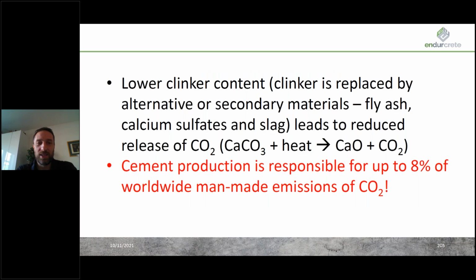And why? Because these new cements contain much less of standard Portland clinker than the ordinary cement, which is demonstrated here in the basic equation. What happens during the clinker production. And simply, if we use less clinker and replace it with alternative materials such as fly ash, calcium sulfates, or slag, this leads to the presented reduction of more than 40%.